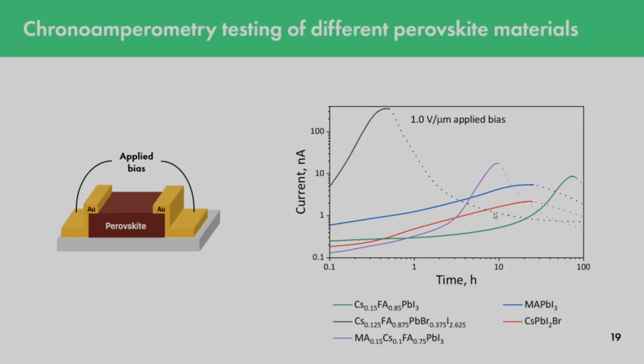This can be explained by a simple process: during the biasing we probably have some ion migration, charge migration that leads to the formation of defects. And at first, at the beginning of the process, these defects serve like electrochemical doping, and this doping leads to the improvement of the current in the channel.